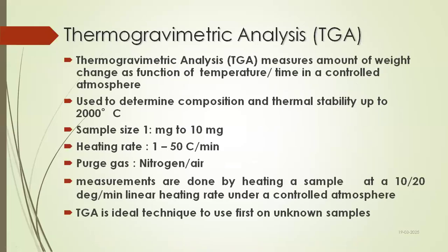It measures the amount of weight change as a function of temperature or time in a controlled atmosphere. You can measure the thermal stability of the material using TGA up to 1000 or 2000 degrees centigrade, depending on the furnace value. Sample size can vary from 1 mg to 10 mg. Heating rate can vary from 1 to 50 degrees centigrade. Even though your equipment allows you to heat at higher rates, in the slides coming up, I will show you why you should not use a heating rate higher than 50 degrees centigrade.